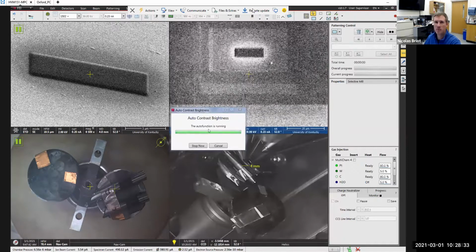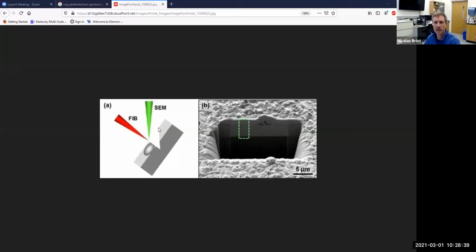So now I'm about to make this large cut. So I need to excavate all of this volume here. And it's really just opening a window so that the SEM can actually see that cross section. So all of this has to go. And to do that, we just really bump up the FIB current.